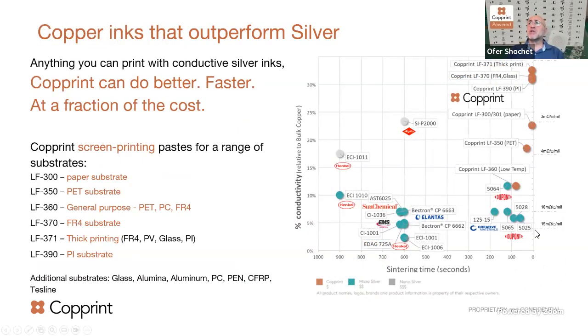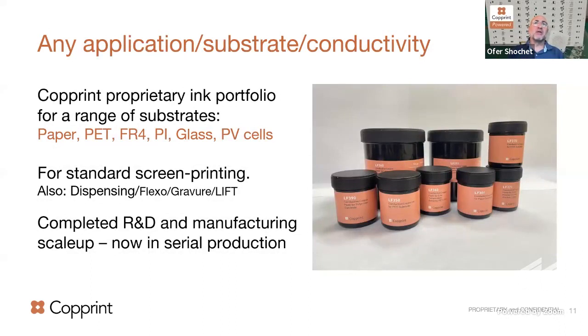With copper inks, you can see on the chart comparison to a lot of silver inks, you can see that the copper ink has higher conductivity and faster processing time. And we have today quite a lot of inks that people can buy in order to print on paper, on PET, on FR4, on photovoltaic cell, and people can use different printing, not just screen printing, as I mentioned, but also dispensing, flexo, gravure, lift, like the presentation of Ralph from IoTech after my presentation, where they are also using the copper ink in their process.